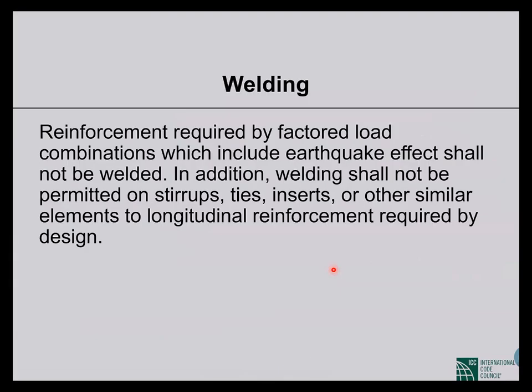Now, another important condition. This is not directly related to concrete material, but it is more related to the detailing part of seismic design, so I want to mention it. This is related to welding of rebars for special moment frames and special structural walls. Reinforcement required by factored load combinations, which include earthquake effect, shall not be welded. So the reinforcement that you are providing for wind load, this restriction doesn't apply to. The reinforcement that is needed to carry earthquake load, this restriction is imposed on it: you cannot weld the longitudinal rebars